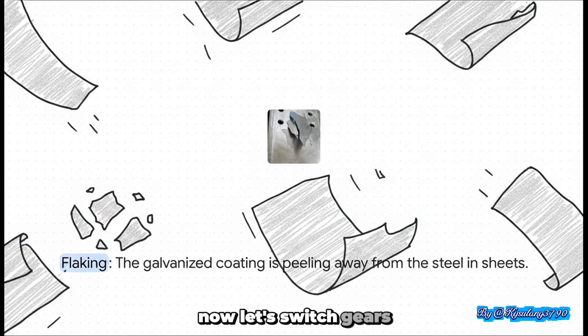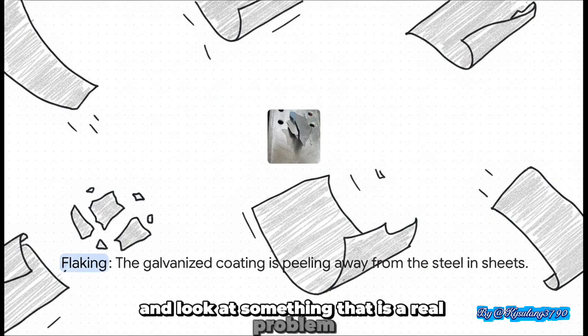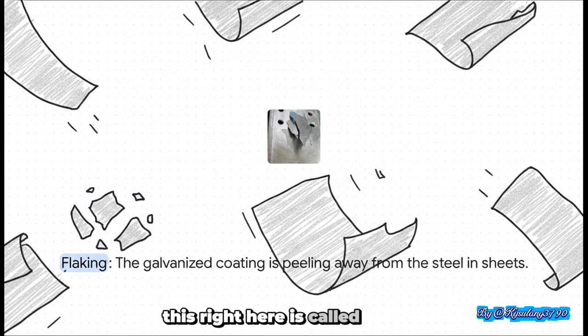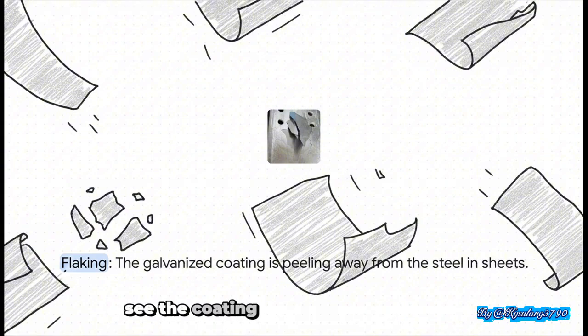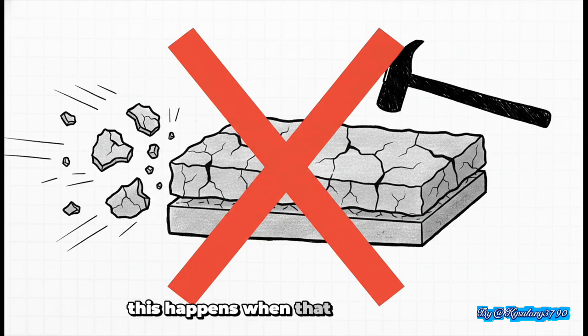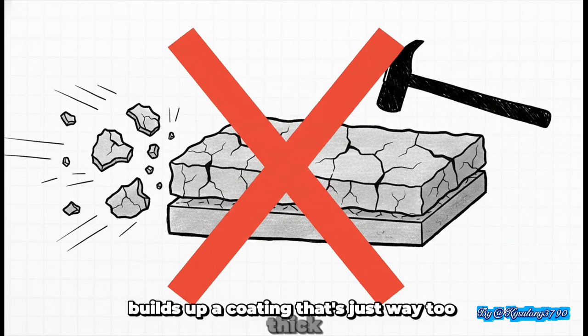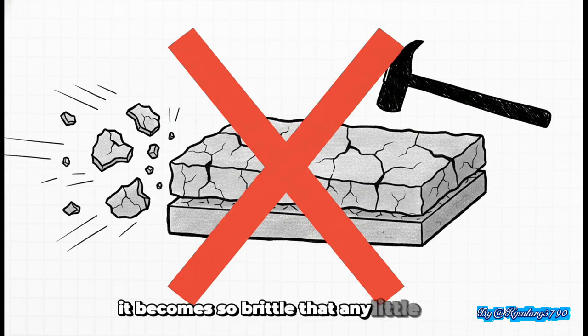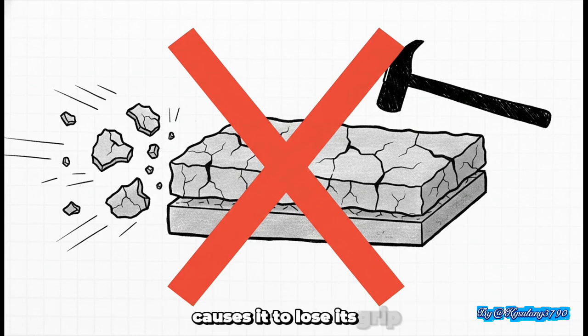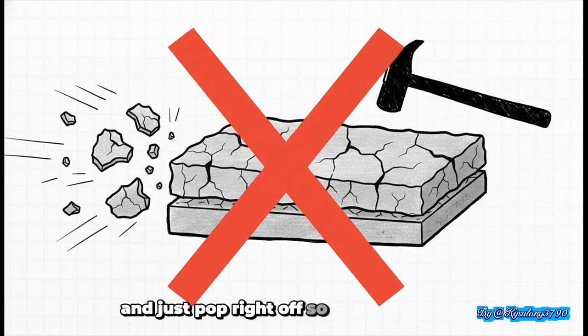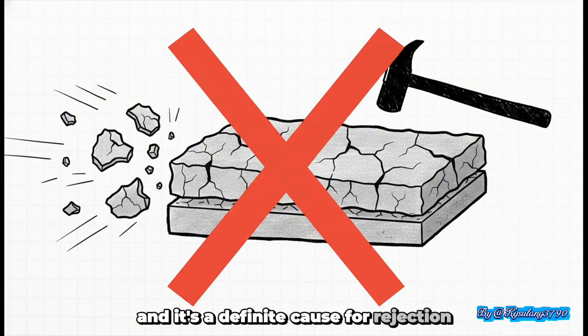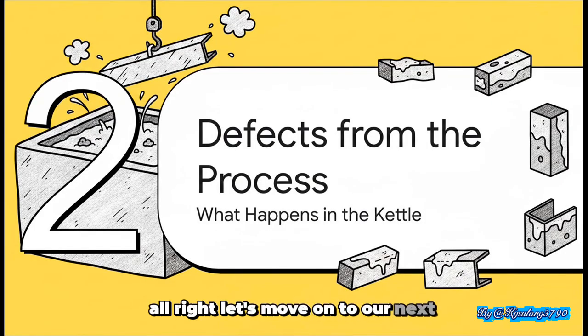Now let's switch gears and look at something that is a real problem. This right here is called flaking. You can literally see the coating just peeling away from the steel like old paint. This happens when that same reactive steel we talked about builds up a coating that's just way too thick. It becomes so brittle that any little bump or flex causes it to lose its grip and just pop right off. So, unlike that dull gray finish, this is a true failure of the coating, and it's a definite cause for rejection. All right, let's move on to our next category.